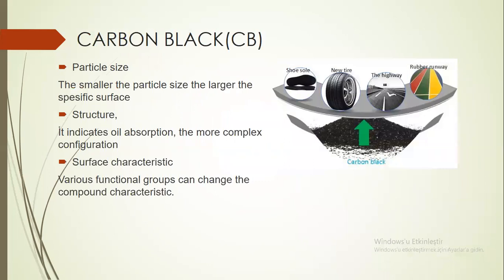Carbon black. The smaller the particle size, the larger the specific surface. It indicates oil absorption, the more complex configuration. Various functional groups can change the compound characteristic. It is a powder waste from the rubber industry and finds difficulty in its disposal. By using carbon black as filler in concrete, we can reduce this problem to a great extent.